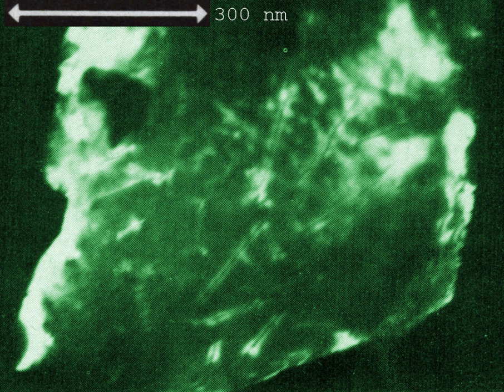Anisotropic conduction. A platform covered with many free-standing wires acts as a large area field emitter. Magnetic multilayers, nanowires consisting of alternating magnetic, non-magnetic layers act as magnetic sensors. As an example, cobalt-copper nanowires are obtained from an electrolyte containing both metals. At low voltage, pure copper is deposited while cobalt resists electrodeposition. At high voltage, both metals are deposited as an alloy. If the electrolyte contains predominantly cobalt, a magnetic cobalt-copper alloy is deposited with a high fraction of cobalt.